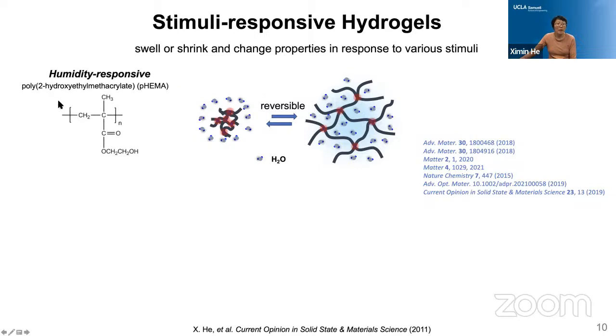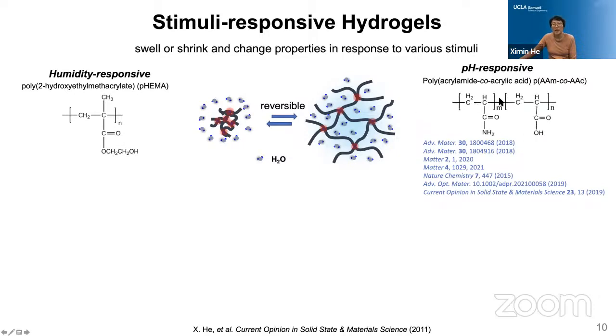And most of the hydrogels are by default humidity responsive, just like our contact lens. If you leave it on the desk or table for hours or days, it will automatically shrink. And if you just re-swell it in liquid, it will swell and volumetrically expand as well, right? And then you can also design your polymer network with polyelectrolyte polymers, so that the polymer may undergo protonation, deprotonation. It will become hydrophobic or hydrophilic to undergo this volumetric change.